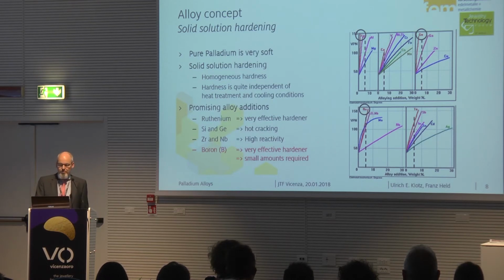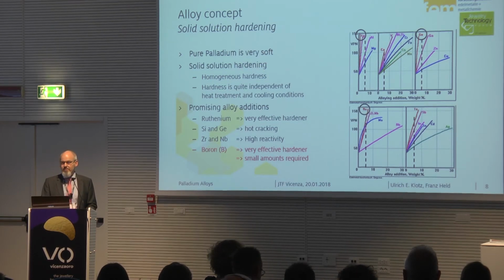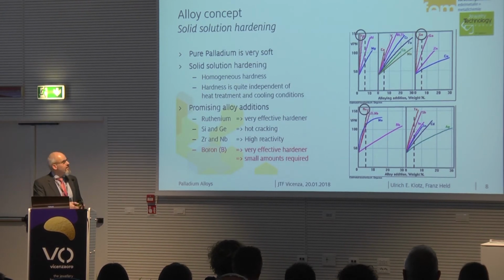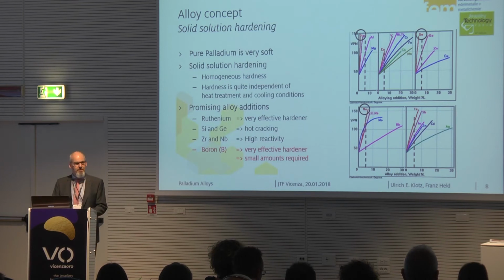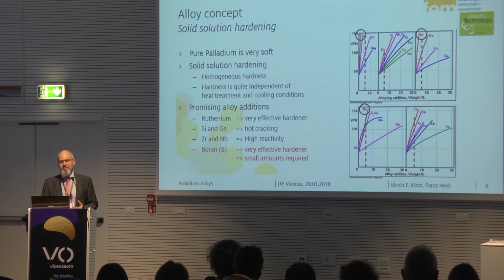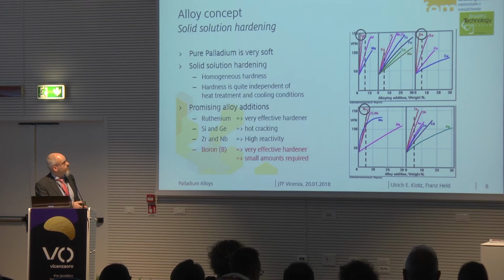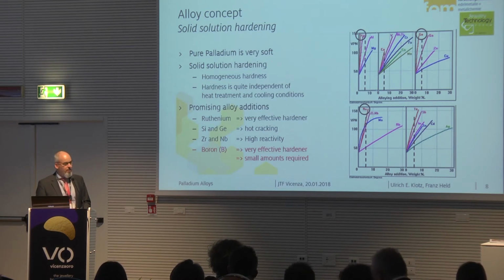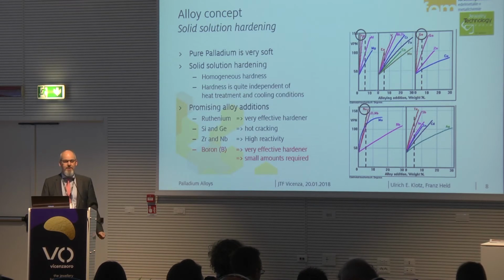But of course, not all elements are suitable. Some of them are toxic, like tellurium. Others, like silicon and germanium, can result in very severe embrittlement, like what I showed you in the beginning. Others, like zirconium, niobium, vanadium, titanium, are very reactive, and they are not suitable for the investment casting processes that are used in the jewelry industry. So, as you see, there are many elements, but only few possibilities remain. Ruthenium is one of the most effective, and boron is also a very interesting element. Boron is interesting because it's a very light element, so you can add only small amounts and get big effects.